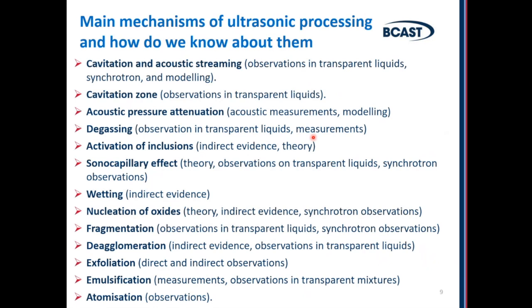So what actually happens when we talk about ultrasonic processing? There are a lot of phenomena which are interesting and relevant to processing itself. First of all, we have cavitation and acoustic streaming, which was illustrated in the previous slide. We can observe it in transparent liquids, now in non-transparent liquids using synchrotron, and we can do modeling. Then we have the cavitation zone, which nowadays we can also observe. We can also measure acoustic pressure in the cavitation zone and outside it, and measure the attenuation, because of course the pressure is maximum close to the source of vibrations, but then it attenuates through the volume.